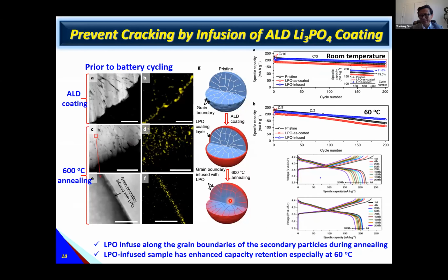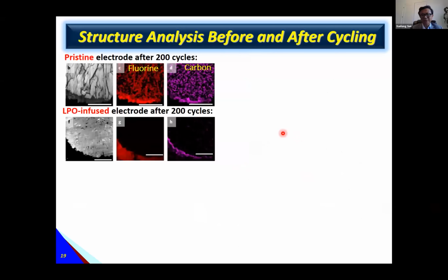So for the performance, here we compare without coating. We see after 200 cycles, it just maintains 79%. But with coating and annealing, we can maintain 91% after 200 cycles at room temperature. And at high temperature there is obviously a big difference. So we also try to understand what the difference is.